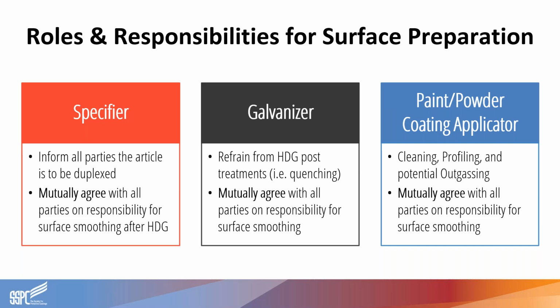Next, the galvanizer and the coating applicator must communicate directly and agree on responsibility for smoothing out any surface conditions that might present a problem for painting. Finally, the coating applicator is always responsible for the remainder of the surface preparation requirements beyond that smoothing, like cleaning and profiling. And in the case of powder coating, they'll also be required to perform the steps to prevent outgassing.